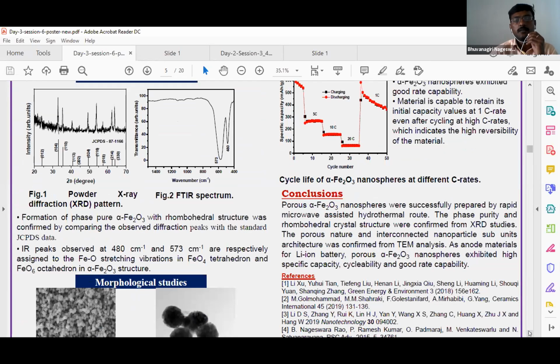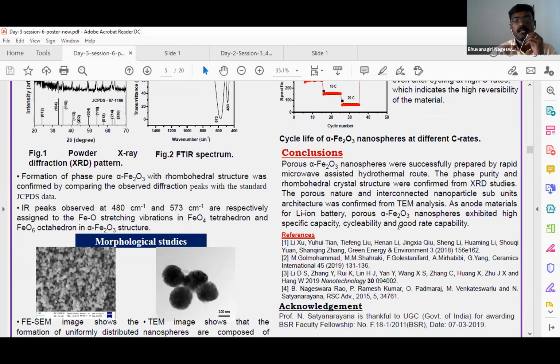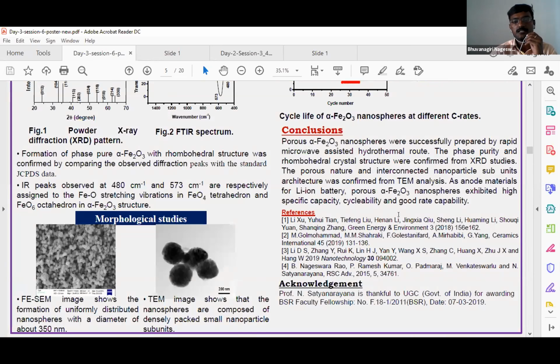Later, we wanted to investigate its stability at high C rates. When we want to draw high currents, we want to check the stability of the material. So we recycled at high C rates like 5C, 10C, 20C also. It exhibited good cycle stability with small reduction in capacity. And further, we recycled the battery at 0.1 C rate to check the recoverability. When we change the C rate from 20C back to 0.1 C, the capacity returns to the initial value, which indicates good reversibility of the material at high C rates.